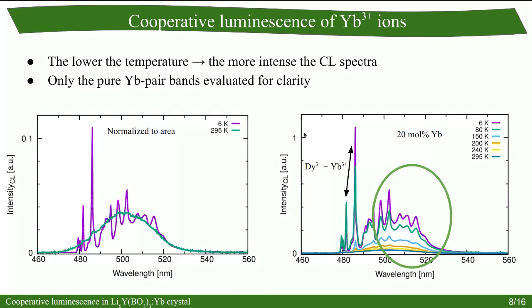After that, we checked the temperature dependence of this cooperative luminescence spectra, and we can see that the bands where we can find both dysprosium bands and ytterbium cooperative luminescence bands have a different temperature dependence than the clearly ytterbium cooperative luminescence bands. So after the measurements, for the fit process, we just use this part of the spectra. So the integrated intensity was calculated from these wave numbers only.